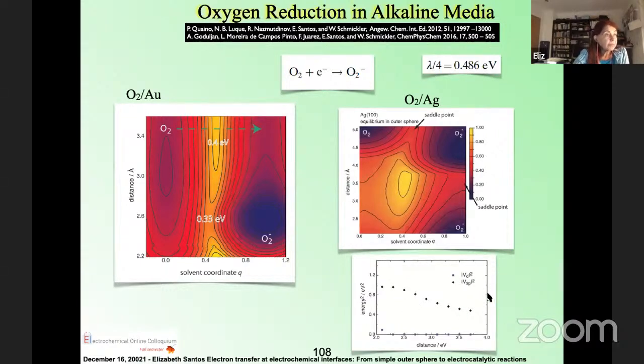And we have calculated the interaction parameters between the d band and the sp band for the oxygen, and we see that they are very low. For the d band it is practically 0, and for the sp band it is very low.